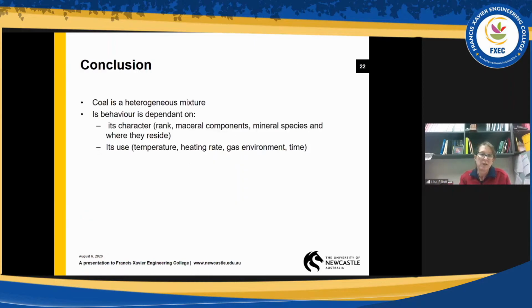All right, so in conclusion, the big points that you need to take from this is coal is a heterogeneous material. It's a very varied substance, even in the one coal. And the behaviour of the coal is dependent on its character, that is its rank, the maceral components, the mineral species that are present in it, and where they reside in the carbon structure. And how it's used will affect what happens. So the temperature, the heating rate, the gas environment, and the time at temperature really makes a big impact. That's where I'd like to leave it. Thank you for your time and your patience.